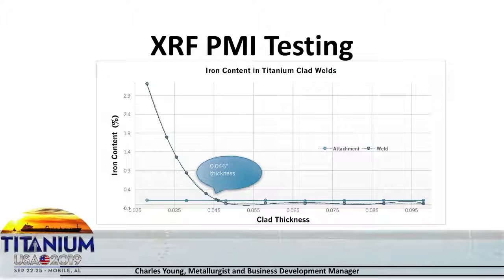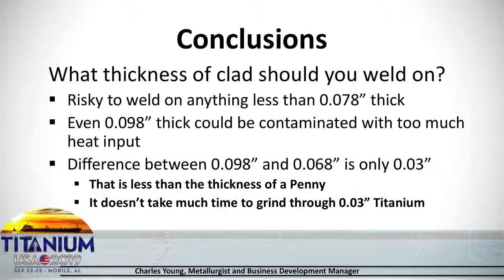And again, this is a chart basically showing that below about 0.048, where's 048 on there? I can't read that. Yeah, right here, before 048, your iron content goes up dramatically, so we would say anything below 048 or 058 would give you a problem. So if you're looking to repair a vessel, or if you're a chemical company repairing a vessel, and you measure the thickness of your clad at lower than that, you might not be able to repair it. So we look at this, and it's risky to weld on anything less than 078.